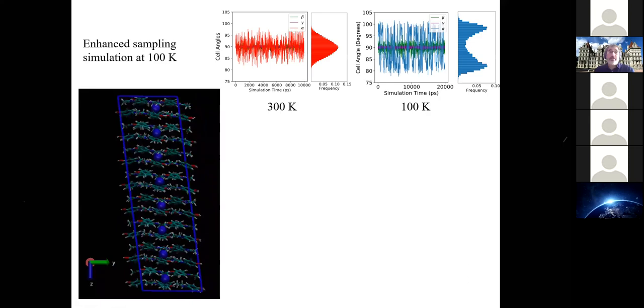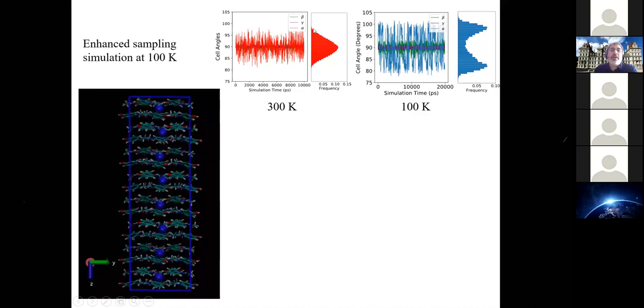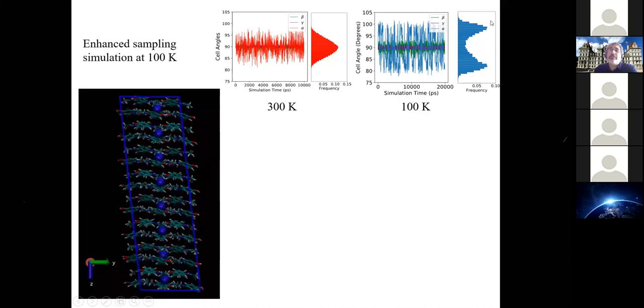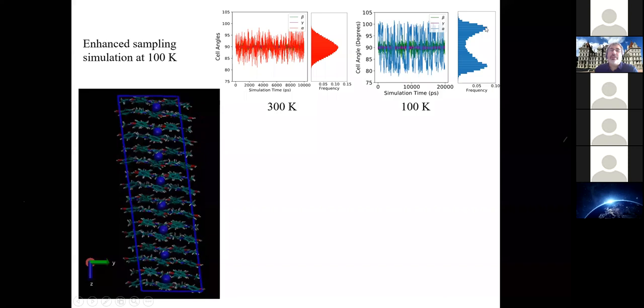And of course, if you calculate from your standard MD at 300 Kelvin and your enhanced sampling at 100 Kelvin, you can see that there's a change in the probabilities associated with one of the angles. It turns out it's the alpha angle in this case. So while at 300 Kelvin there's a peak in the histogram at 90, at 100 Kelvin the histogram peaks at values around 82. And of course, there's an image of this around 107 or so.